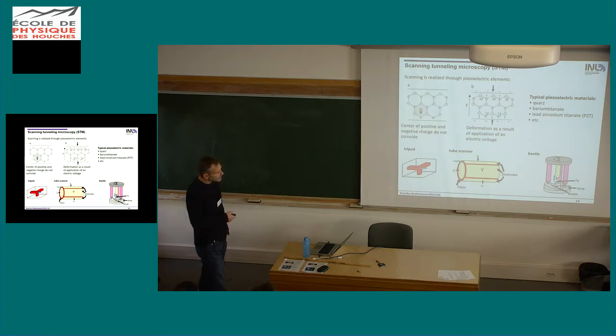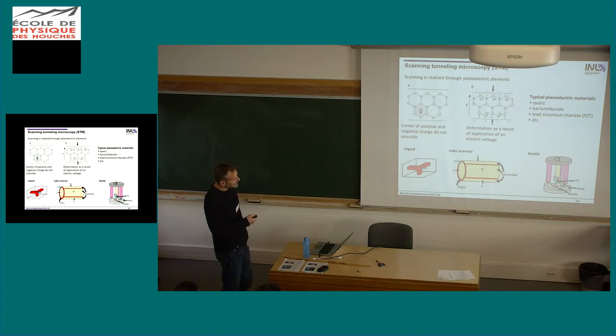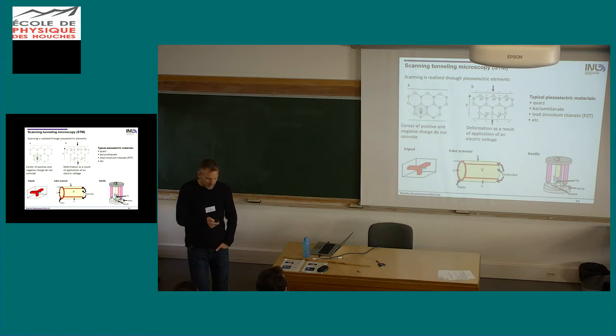But then to approach it, of course, you cannot look at how far you are from the surface at this dimension. So you do this optically. You bring this very close. And then you apply a stick and slip motion to bring this whole tip down these ramps into close proximity. We are talking a few angstroms distance, so that you can actually get a tunneling current appearing between the sample and the tip. So this is more the type for the coarse motion.